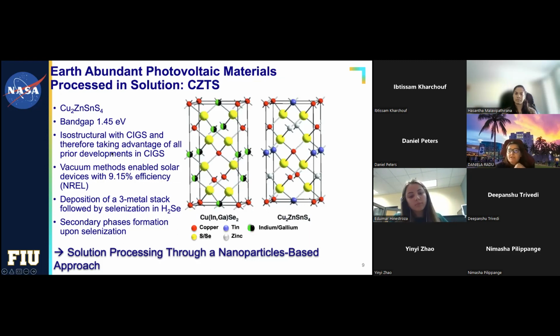So, mentioning earlier, the CIGS was produced through vacuum methods. They obtained a mere 9.15% for this copper zinc tin sulfide when they used vacuum methods. Okay, so unfortunately, another problem was that this stack of elements had to be selenized in a gas. This is a toxic gas, hydrogen selenide, okay? So there were many, many problems to making these materials, copper, zinc, tin sulfide. No matter how nice and isostructural and composed of very, very high abundance elements on Earth crust, it would not be a sustainable process. The material is great and sustainable and green, but the process is a disaster, okay?